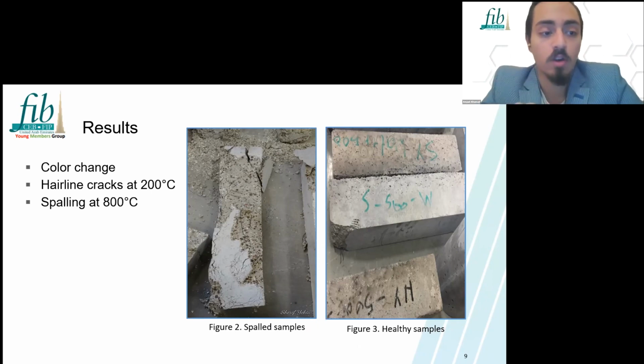Both lightweight concrete mix and steel fiber lightweight concrete mix, the prisms in both mixes, changed to a darker color at 500, then returned to the light color at 800 degrees Celsius. In terms of the element itself, the concrete started to develop hairline cracks at 200 degrees. Then at 500, the cracks became more uniform on the concrete surface. Plus, at higher temperatures, such as 800, which is the highest temperature we had in this study, few samples spalled inside the furnace. These are just observations of the elements so far.